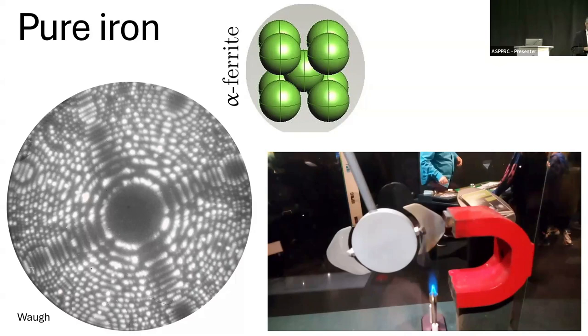So you can tell a lot of what I'm going to say to your friends and your family: look, you owe civilization to the magnetic properties of iron. If you do first principles calculations, without magnetism it would be the hexagonal form of iron which would be stable under ambient conditions. And we know the limitations of hexagonal structures in terms of the numbers of slip systems